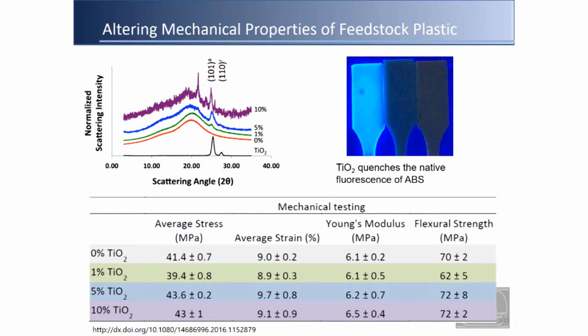So what do you find? Well, when you look at the X-ray diffraction spectra, in fact, when you print the piece, titanium is throughout the entire piece. So that's good news. It's not sort of clustering out in one giant chunk somewhere. Its presence definitely changes the optical properties of ABS. So its native fluorescence is being quenched.